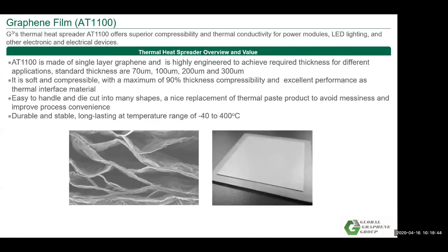Another key product is AT1100, which we have developed in the past years. In contrast to AT1500, AT1100 is a low density thermal film. It was developed to target thermal interface applications. It offers low thermal resistance and gives you the option of through-plane dissipation of heat from the heat source to a heat sink. We can offer 70 microns, 100 microns, 200 microns to 300 microns. Such film is also very stable.